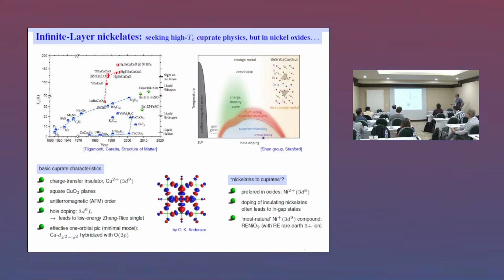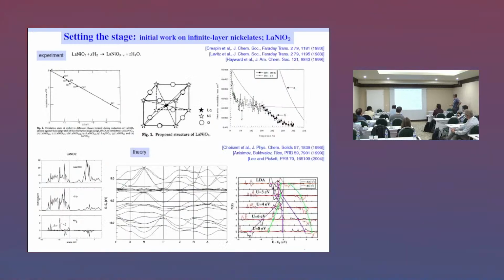But there are some complications coming quite easily, because nickel usually prefers the nickel 2+ 3d8 configuration. If you dope the known insulating nickelates that we know, for instance the cuprate sister compound 214 nickelates, then you get all kinds of in-gap states, not nice metallic states, or you also get nickel oxide for the Ruddlesden-Popper compound. So this is a bit difficult, and one has to understand very, very deeply these effects of doping in these oxides, to my thinking.